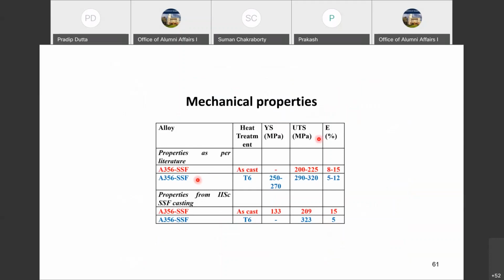And what we see here is that when we use the finished part and we do a heat treatment, as per literature, this was the range of yield stress and UTS, and we found our UTS actually exceeded that. UTS exceeded what was there in the literature. So we were convinced that the properties were good.